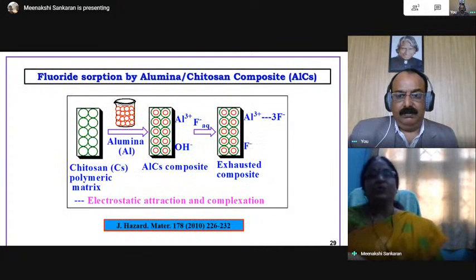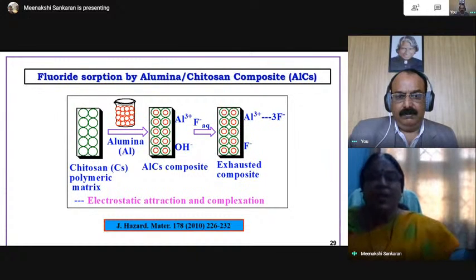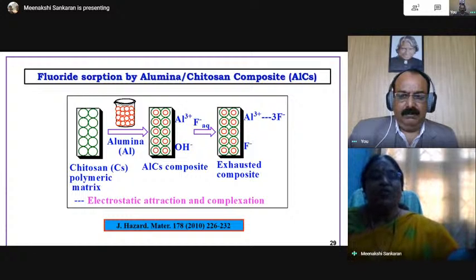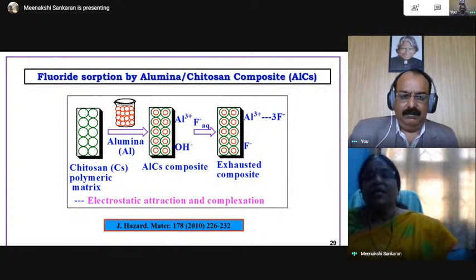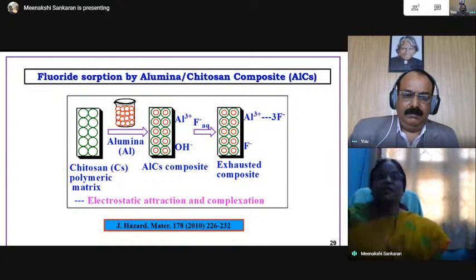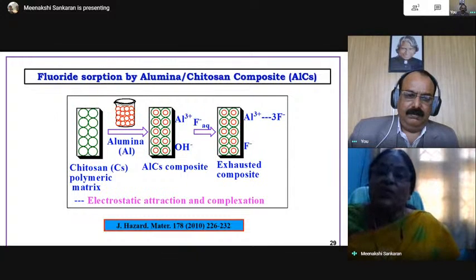And we have also used some composites. As I told, we have mixed chitosan and inorganic material. For example, alumina is highly effective in removing fluoride, but it is somewhat rigid and in powder form. And chitosan is somewhat flexible. When we mix alumina and chitosan, they are compatible with each other, and this composite can be made into bead form or candle form, so that it can be used for making water filters. So technology transfer is easy with these composite materials.